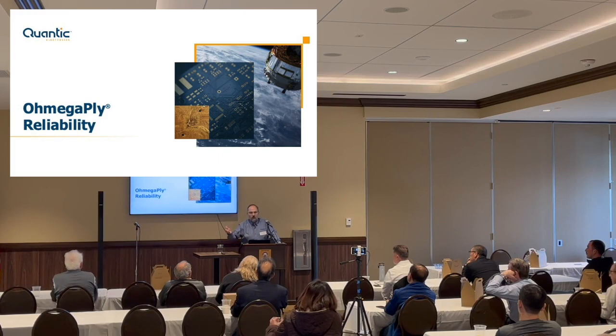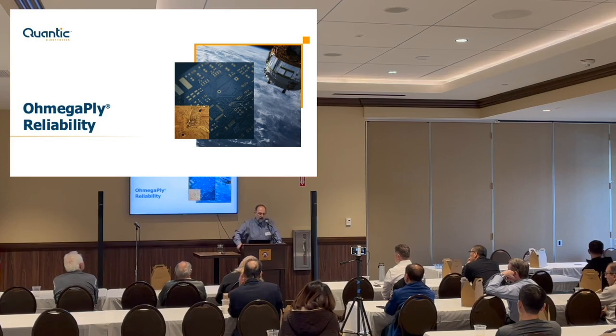So anyway, you can then trim to get the tolerance that you need. In fact, in the biomedical application I was talking about earlier, they put the resistive material on the surface and they trim themselves, because they have to do it as part of the overall system. So they actually use the trim to tune the whole circuit, and they do that themselves. So laser trimming is very common, and this material is so thin it doesn't take very much energy to do it.